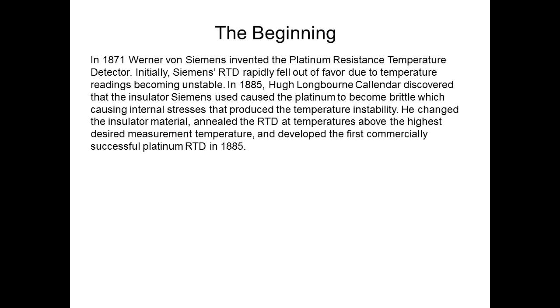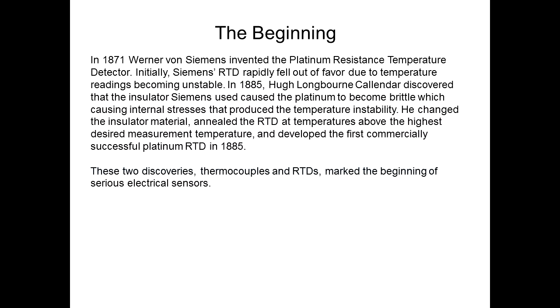Initially, it fell out of favor due to temperature readings becoming unstable, and Hugh Longbourne Callender discovered that the insulator that Siemens was using was causing the platinum to become brittle, which caused internal stresses, and that produced a temperature instability. He changed the insulator material, annealed the RTD at temperatures above the highest desired measurement temperature, and developed the first commercially successful platinum RTD in 1885. These two discoveries, thermocouples and RTDs, marked the beginning of serious electrical sensors.